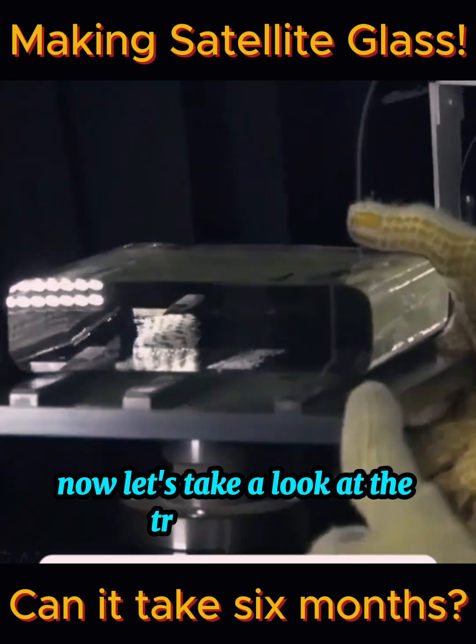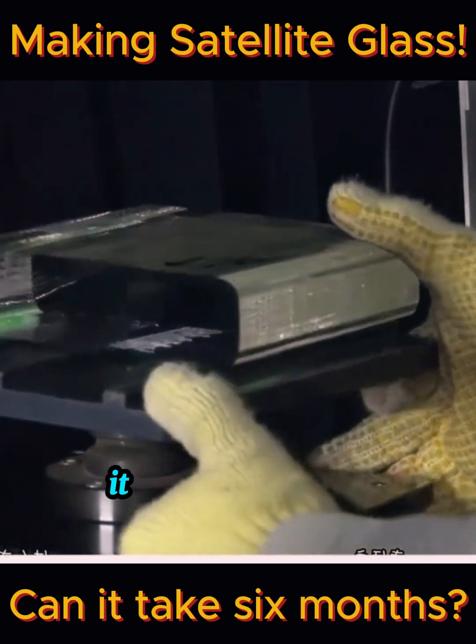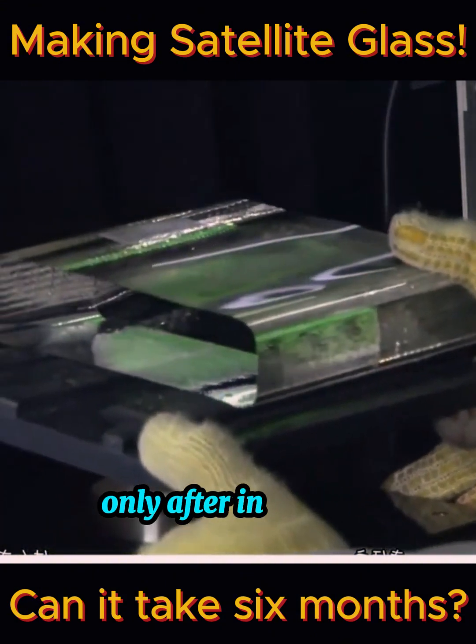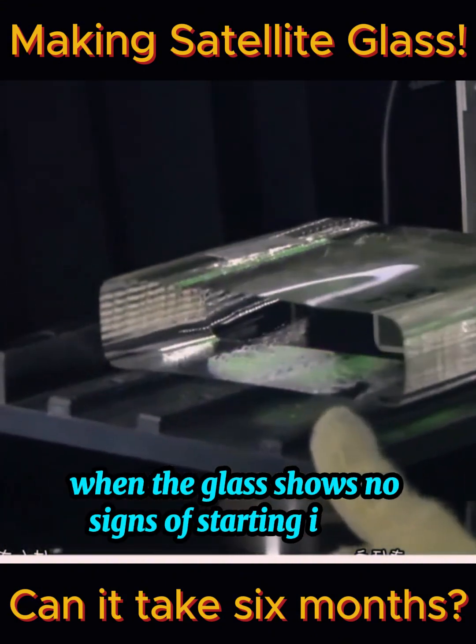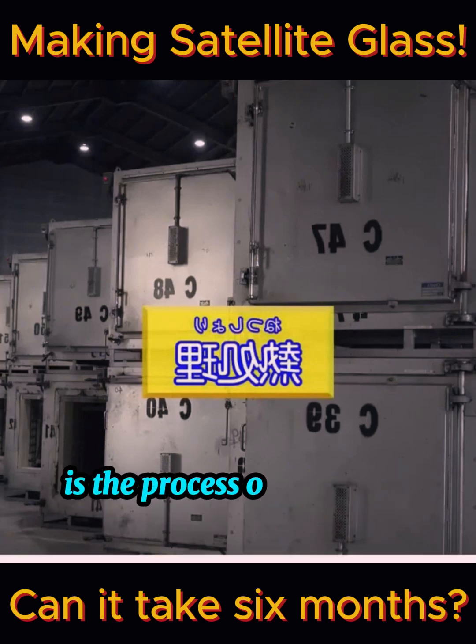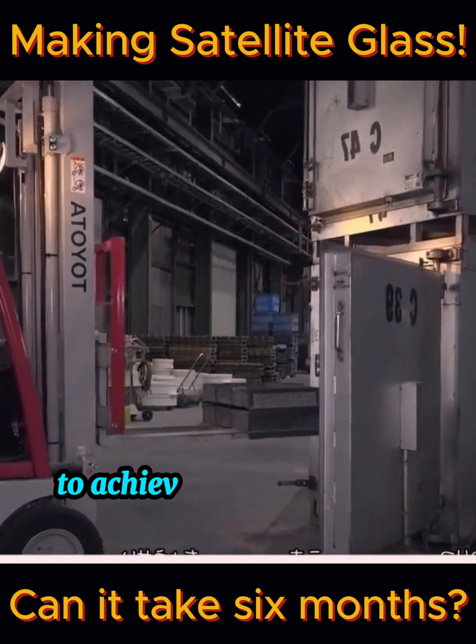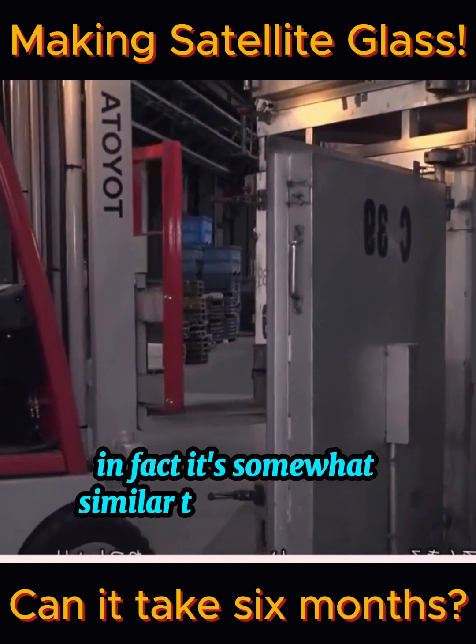Now let's take a look at the transparency. Compared to ordinary glass, it's truly a world of difference. Only after inspection, when the glass shows no signs of starting issues, will it proceed to the next step of heat treatment. The so-called heat treatment is the process of changing the glass's rigidity through temperature to achieve a homogeneous treatment. In fact, it's somewhat similar to quenching in metals.